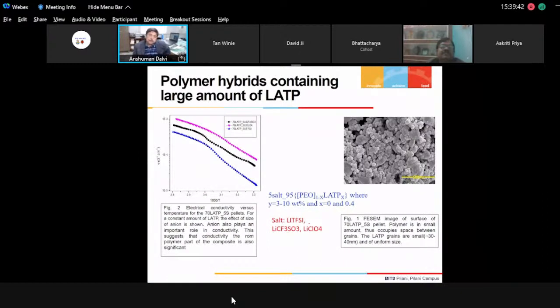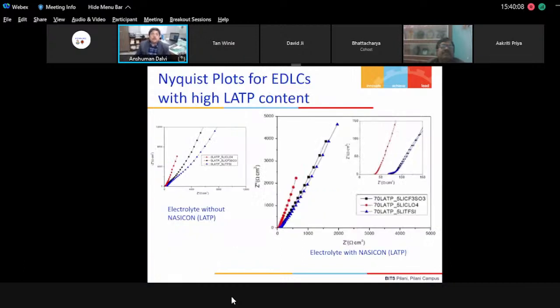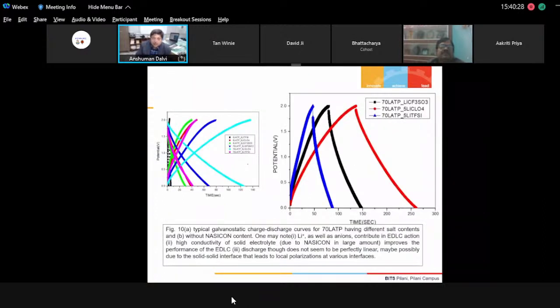Now, when the conductivity of the polymer electrolyte is improved by adding more Nasicon to it, that means the polymer is going into the Nasicon matrix and sitting between the grains and grain boundaries, then the conductivity in certain cases is certainly higher than 10 to the power minus 4 at between 30 and 40 degrees Celsius. And these are more useful systems for fabrication purposes. So when one uses high Nasicon content samples for the fabrication of EDLCs, the impedance value is also quite low, and the overall discharge shows a higher capacity.